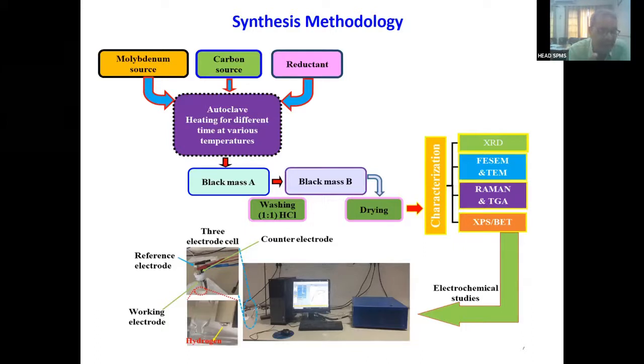So what we have done is, in the autoclave hydrogen is produced, and it diffuses along the grain boundary and breaks the material into very small, nano-size pieces. Whatever oxides you take are converted to small-size nanoparticles, and on those smaller nano oxides, carbon is deposited. Slowly, because of the higher temperature and with the passage of time, carbon diffuses inside the material. So the outer layer becomes rich in carbon, and the inner core becomes less rich in carbon. Once you perform the experiment for a longer duration, you have to optimize both time and temperature, and the entire oxide is converted to carbide here.